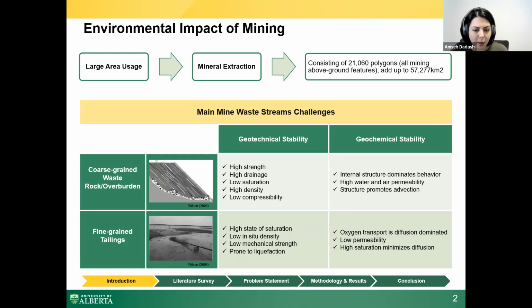So tailings have a high water content with an initially low in-situ density and low mechanical strength, which makes these structures prone to liquefaction. In terms of geochemical stability, tailings are typically saturated with high water content, which leads to a low diffusion coefficient, and low diffusion makes tailings chemically more stable than waste rock piles, since oxygen flow is very limited. However, unsaturated tailings in sand embankments and beach sediments are free to oxidize and generate acid rock drainage when exposed to oxygen.